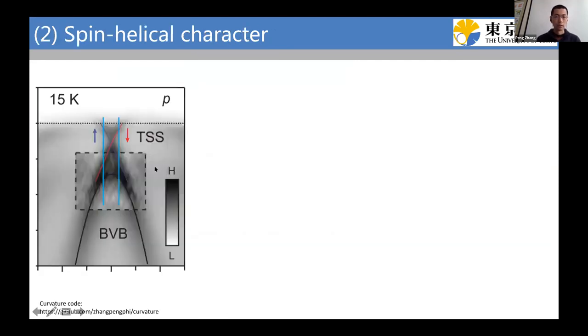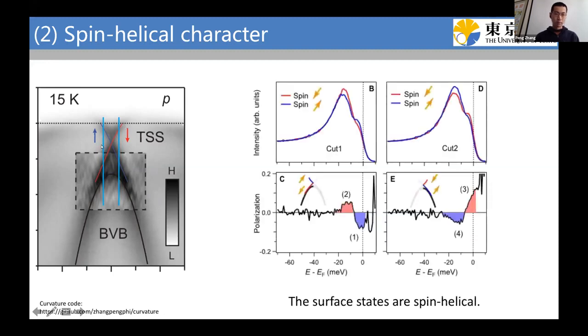A more direct method to confirm the surface origin of this cone structure is the spin polarization measurement. Actually, this is the most difficult experiment in this project, since for spin polarized ARPES the efficiency is very low. It took me more than half a year to optimize the energy resolution and to figure out the proper configuration. At last, I found clear data. We see that near the Fermi level, there are spin polarized states. At slightly higher binding energies, there is no obvious spin polarization. This spin polarization switches sign from below the Dirac point to above the Dirac point, from the left side to the right side.